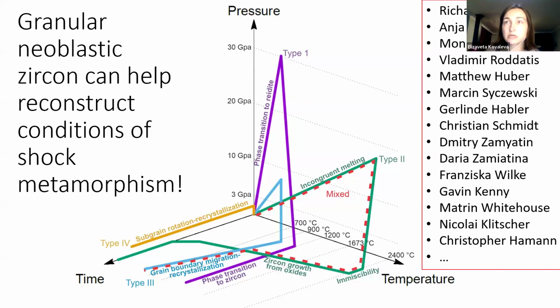Speaking personally, we did this with Araguainha granular zircons, and we roughly got the age. We wanted a more precise age, because there have been some arguments, but the granules from Araguainha are quite small, and there are a lot of small inclusions, so the analysis, the SIMS we did in Stockholm, gets contaminated. We got a very rough age of the Araguainha impact event, but not more precise than has been done before. In that case, it was a bit disappointing, but various impact structures get dated using those neoblastic zircons.